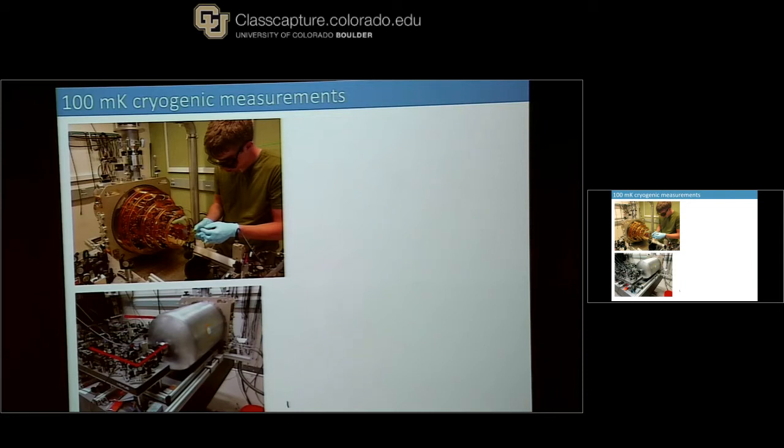Okay. Yeah, so the thin film that we're using is niobium, and I'll show some pictures of that thin film later. And recently we've been doing work with niobium titanium nitride as well in order to deal with some noise problems that we've been seeing, and that also has an even higher Tc.